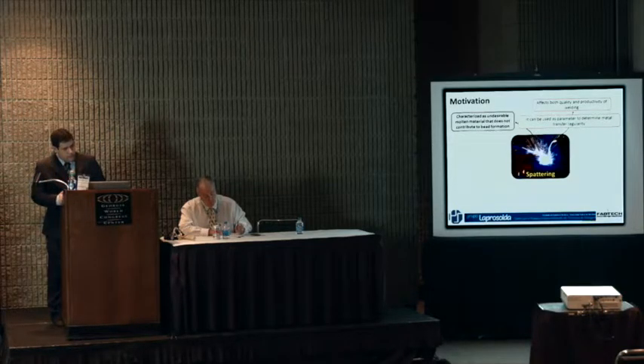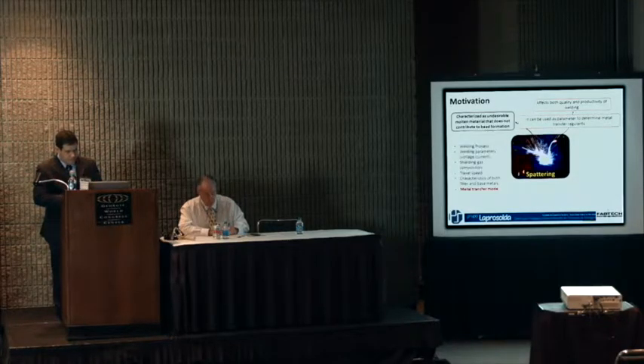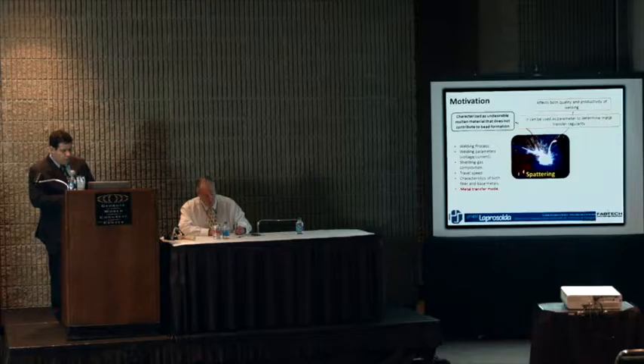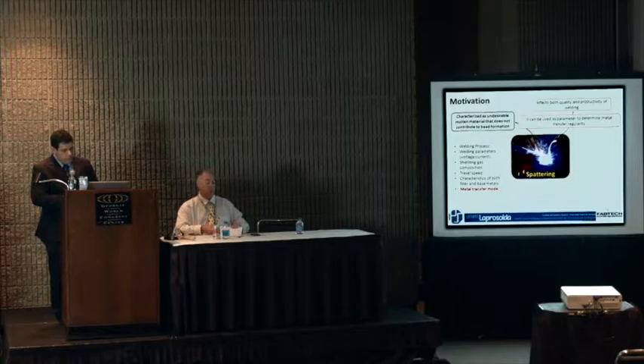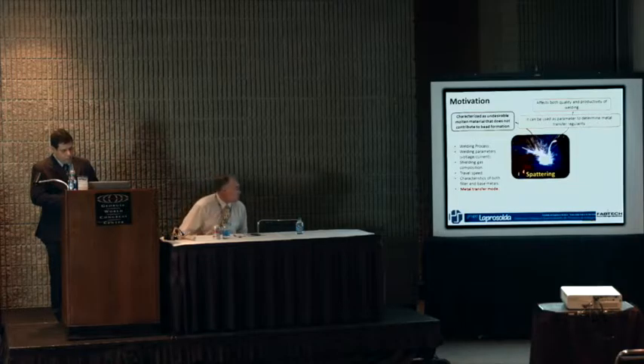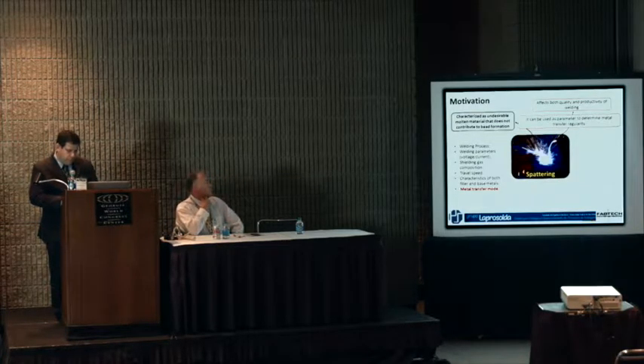The idea of reducing spattering is that we can try to accomplish it by establishing better weld parameter regulation and setup. We can work on the welding process and the parameters themselves: whether it's a constant voltage or constant current power source, the shielding gas composition, travel speed, and parameters in general, and both filler and base materials. But in this particular case, I deal more with metal transfer, especially short circuit, in gas metal arc welding.